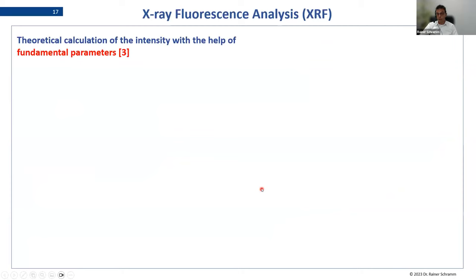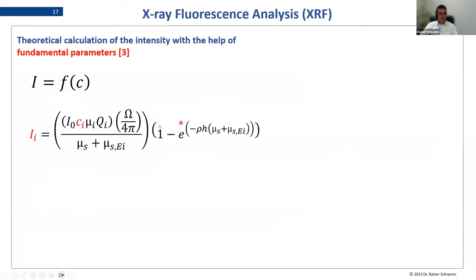So last but not least, we come to the real use of fundamental parameters by calculating the whole approach. That means we describe everything between concentration and intensity by the theoretical approach, by the Sherman equation. And that means in theory, no standard material is used. In the real world, I would always use some standard materials, at least to get the sensitivity of the spectrometer and also to verify the model. But from the theory side, no standard material is used if all conditions of these models are fulfilled.